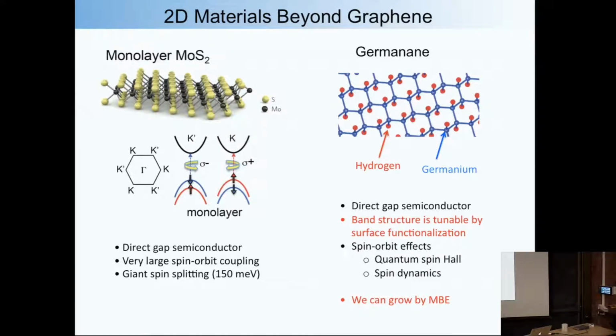There's this material that we've been playing with since the summer. It's called germanane, and I want to spend more time on this. So this is like graphene, except you replace the carbon with germanium, and you tack on hydrogen. So it's more like graphene. So this is germanane. It's a direct gap semiconductor. The band structure is tunable, at least theoretically, by changing the hydrogen to other functional groups.